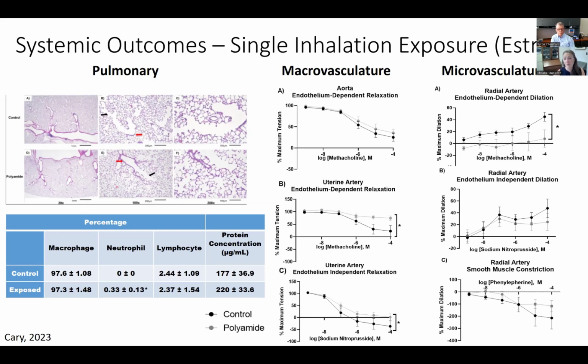So we looked at the pulmonary system, we looked at the cardiovascular system, both the microvasculature and the macrovasculature. We did see some endothelial dependent differences and even endothelial independent differences in our uterine artery, in our radial artery, as we get closer to that fetal area or to the uterine horn itself. So we did see some vascular outcomes despite not seeing any pulmonary outcomes.